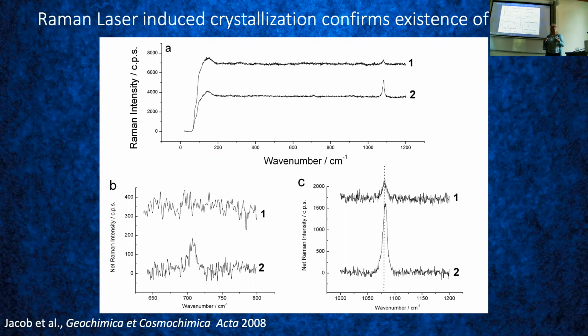And we found then later on, after 10-15 minutes, when we took a new spectra on the same point, that in the meantime, the whole shell had crystallized more. So that is really a very clear evidence that we are not measuring organics, we're actually measuring calcium carbonate, and it is amorphous in the shells.